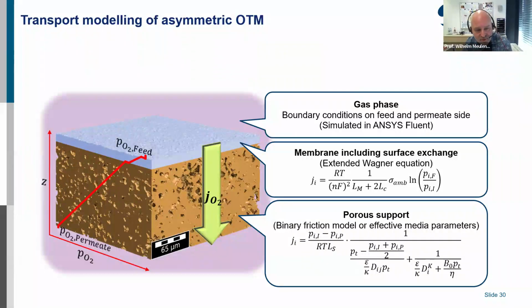But if you put it in a membrane reactor where you have a high driving force, for example, on one side you have methane with a partial pressure of 10 to the minus 20, on the other side you have air, with 0.21 partial pressure, then in principle you have a large driving force.